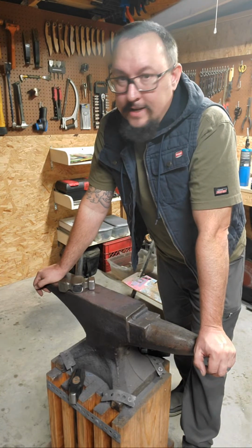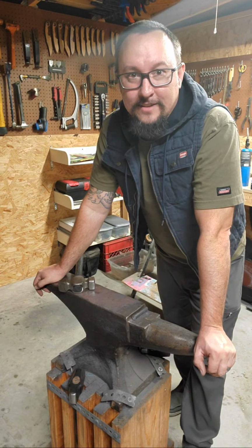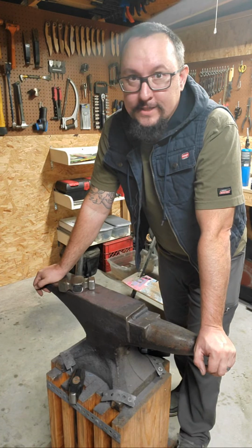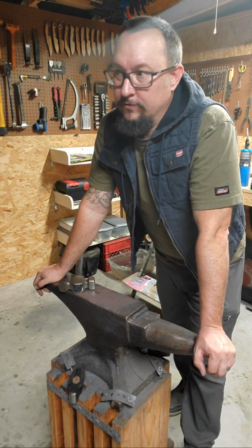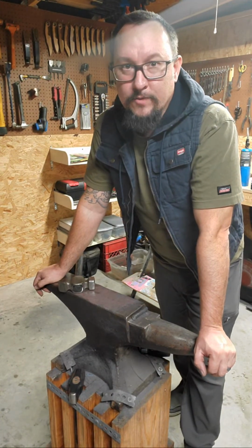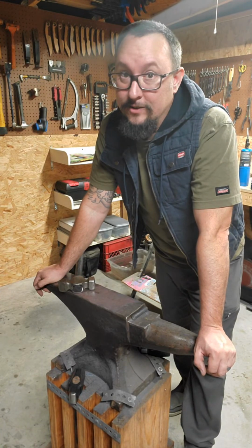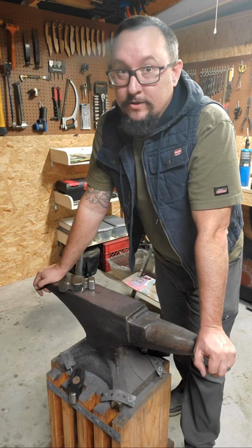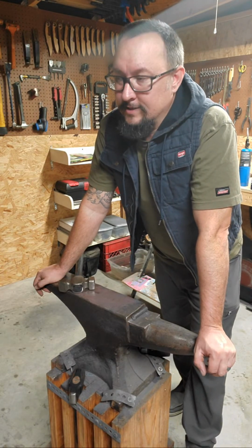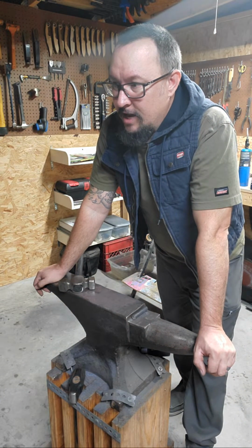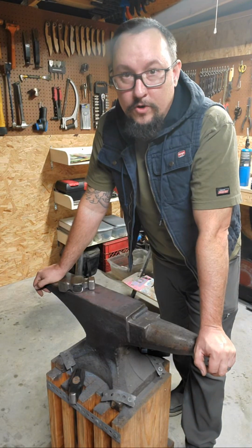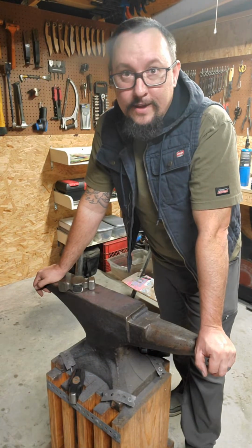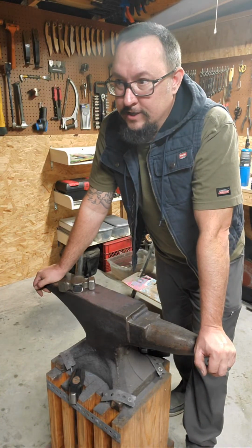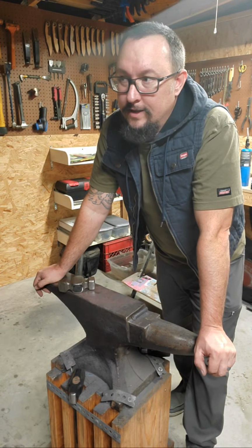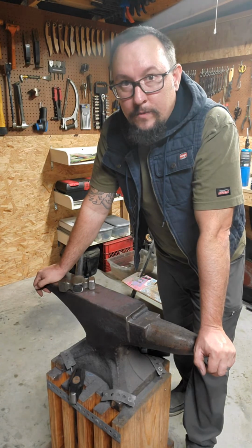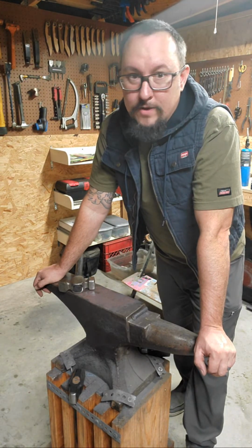And then you think, well, I did an annealing step, but really you only did a thermocycling step. You only did a grain refinement. So you never took it to 1600 to relax the steel. You did 1400, and then you bring it up to what you think is around 1475 or 1500, but it might still be right below 1400. Because it's a nice solid orange, and it's darker in your shop, you go to quench, and either you don't quench it hot enough and it doesn't harden enough, and boom, you're wondering why your steel is 55 HRC and not 65, or you're wondering why you have a big bow in it now.